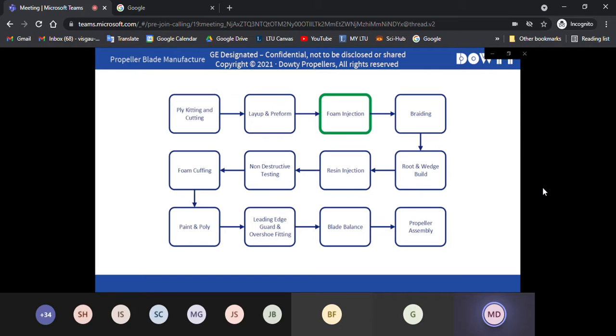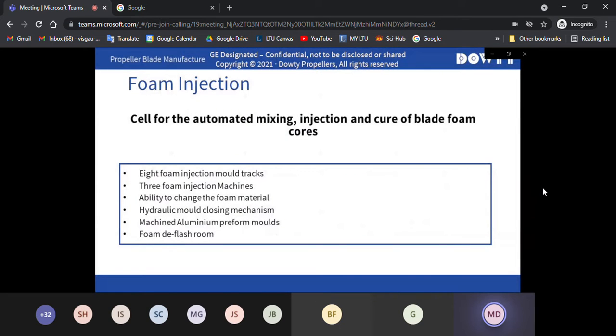And that foam injection process takes place in an automated foam injection cell. So that consists of 3 central foam injection machines. So they handle all of the chemical mixing and dosing and injection at correct temperatures and flow rates into the mold. And each one of the 3 injection machines is mounted on a sled so that it can be repositioned quickly to service multiple injection stations. And these injection stations consist of a clamshell mold, which is hydraulically controlled to allow it to be opened flat and then closed shut for the injection, and also contains automated heating, cooling, and pressurization equipment.